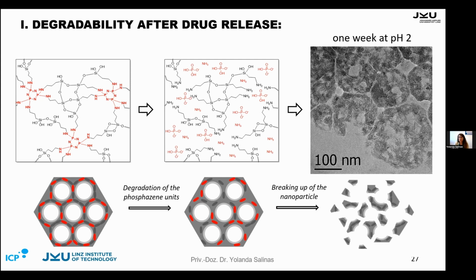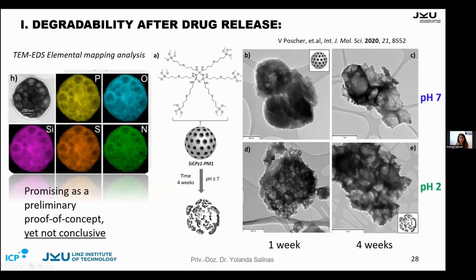As we can see, this was one of the promising results we obtained: after 1 week at pH 2, the nanoparticles actually start degrading or decomposing. A second aim was to create the porosity that we were expecting, because we want to have a very nice hexagonal arrangement of pores. But somehow we were not able to obtain this porosity, but a different type of porosity, more like a foam.